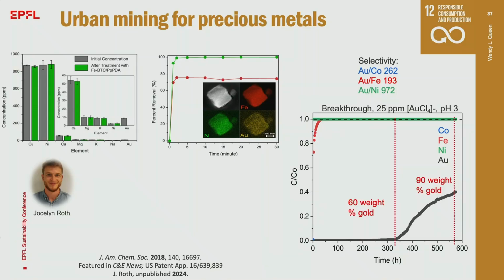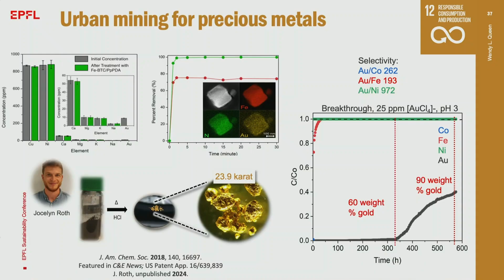And so here, what you can see is at this point, we've reached basically 60 weight% gold, so that means 600 milligrams of gold inside 1 gram of material. Then the extraction process begins to slow a little, but we still get up to nearly our maximum capacity of around 90 weight%. Okay? So from there, we can simply take the material, because it's a high-value target, we destroy the material, and then we're left with 23.9 karat gold on the back end, which is the highest purity reported to date, and this is partly due to the material's high selectivity.